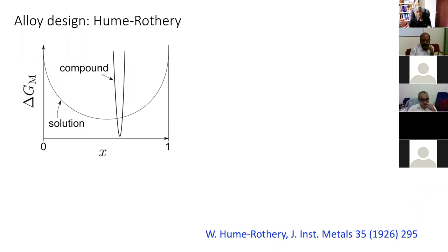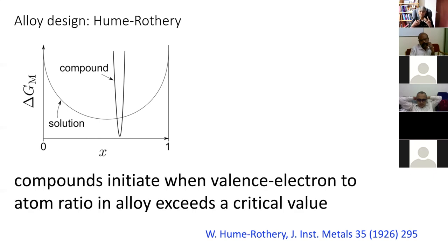Okay, and just to distinguish between a solution and a compound, a solution is something where you can get solubility over a large range of compositions. Whereas a compound also has flexibility in its composition, but it's a very narrow flexibility because the free energy increases rapidly as you deviate from some sort of a stoichiometric composition. So compounds, according to the empirical rules of Hume-Rothery, initiate when the valence electron to atom ratio exceeds a certain critical value.